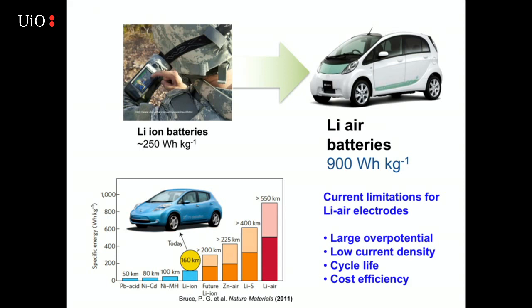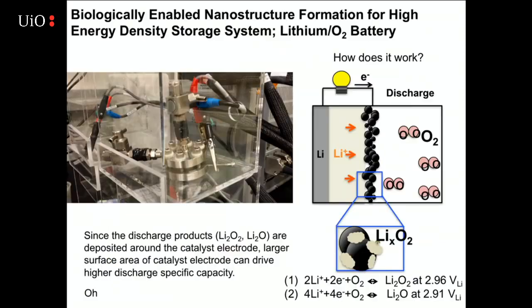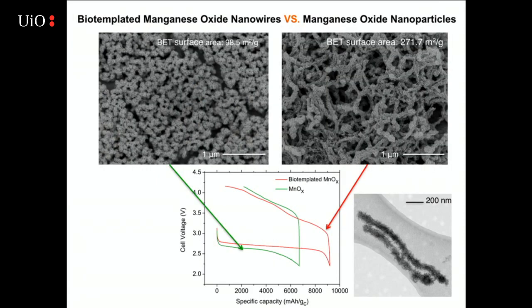And so we said, well, we really need to work on these kinds of materials. But there's a lot of limitations to these. There's large overpotential, low current density, cycle life, and cost efficiency. So what my students decided to do was to work on the catalyst electrode for a lithium-oxygen battery electrode, and see if we could grow one that would perform well. And the idea was that it would also be good at allowing the reversibility of the lithium peroxide during this reaction. And so here's what our virus-based manganese oxide nanowires look like.